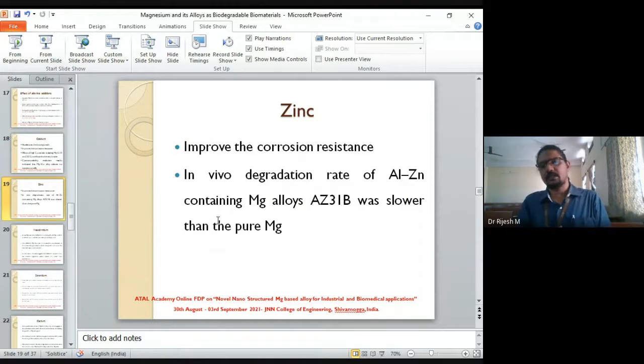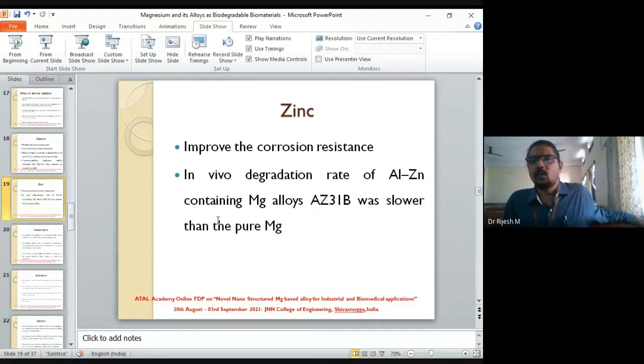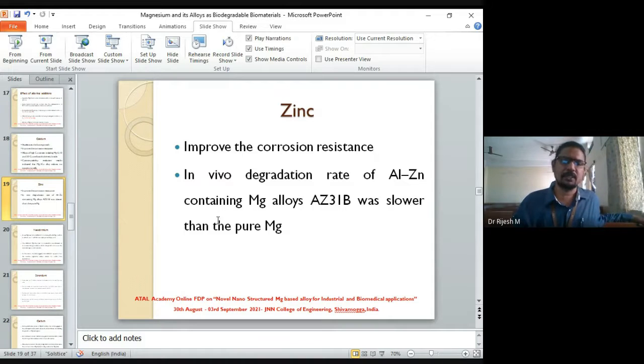Zinc is another metal which improves the corrosion resistance. The in vivo degradation rate of the aluminum zinc containing magnesium alloy AZ31B was slower than pure magnesium. People have done a lot of studies on this and found that when you add zinc, your corrosion resistance improved drastically.